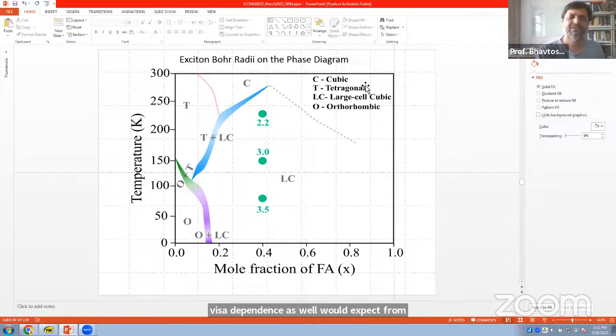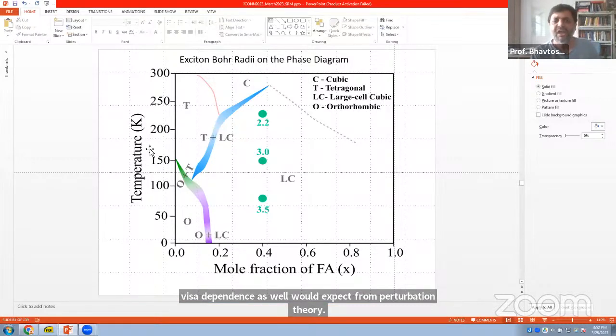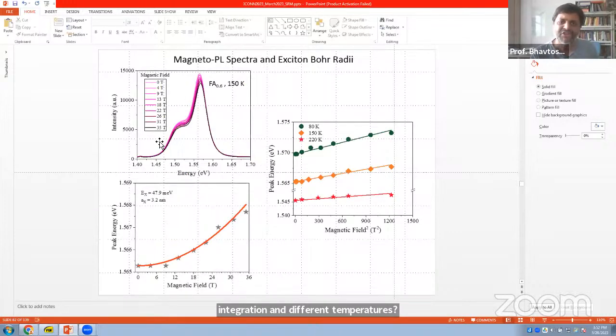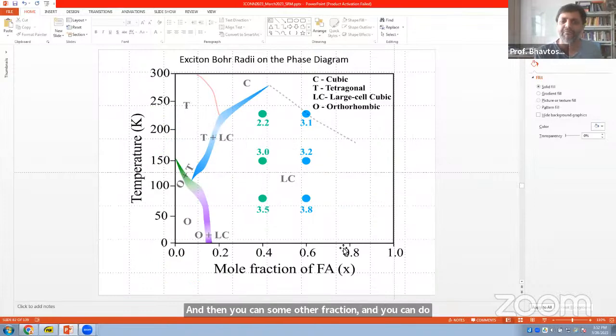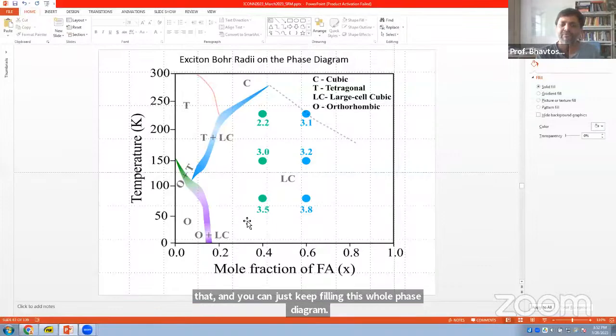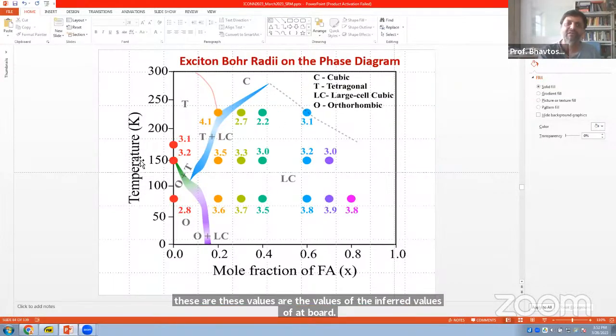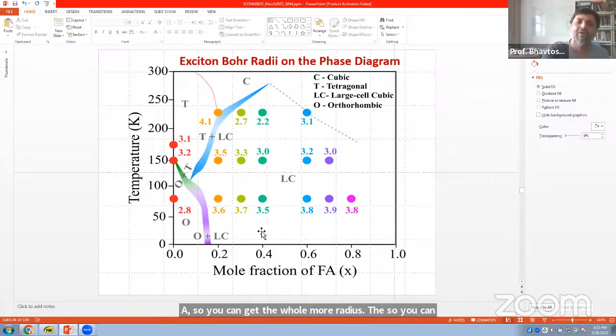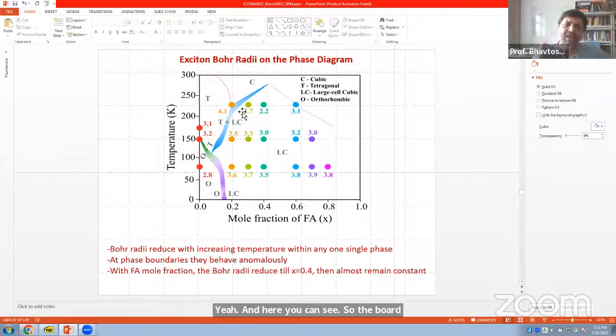What we have done is keep doing these measurements at different temperatures and different fractions, so you can fill in this whole phase diagram. These are the inferred values of the Bohr radius, so you can get the values of the Bohr radius across the plane pretty much. Here you can see the Bohr radius seems to reduce with increasing temperature, and also as you increase the mole fraction of FA up to around 0.4, after which they seem to stabilize.